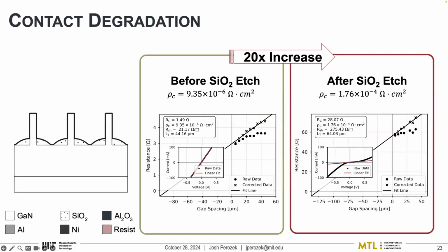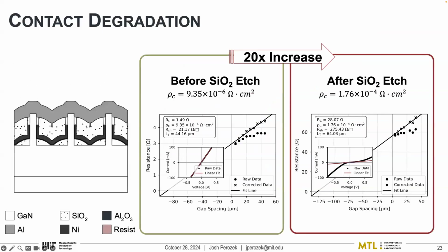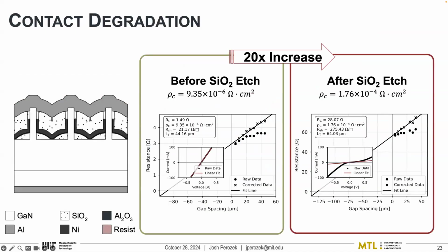And what we found is that all of these etch back steps, where you put the silicon dioxide on and etch the silicon dioxide back, are exposing the gallium nitride to a bunch of fluorine ions. Those implant themselves into the surface, they cause damage, and it degrades the contacts. We see like a 20x increase in the contact resistance, and that's being generous. It's incredibly non-ohmic, so you can't even really talk about contact resistance in this sense.